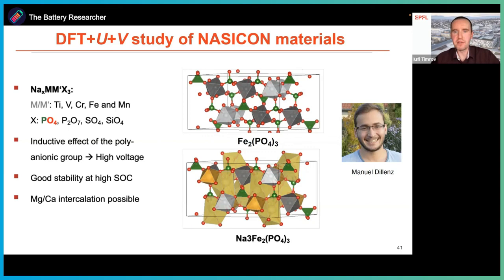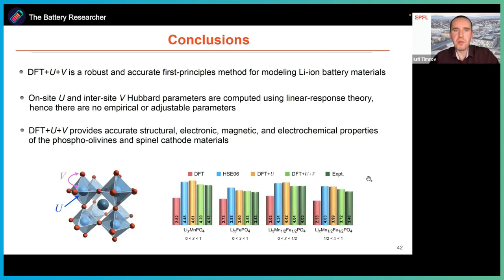And with this, I think I can conclude my talk. I hope I convinced you that DFT plus U plus V is a robust and accurate first principles method for modeling lithium ion, but also other types of battery materials. I would like to remind one more time that often in the literature, people use empirical Hubbard parameters, while we have developed methods that allow us to compute Hubbard parameters for any material and describe very accurately local changes in the local chemistry during the operation of the battery, such as lithiation and delithiation. And also on the examples of phospho-olivines and spinel cathode materials, we have seen that electronic and electrochemical properties are quite well described and in good agreement with experiments.